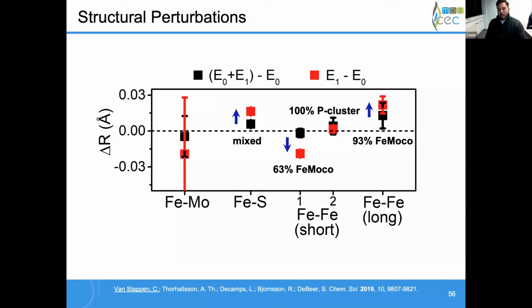and a little bit less so for the short iron-iron, but still reasonably. We also see that for the second short iron-iron distance, we really have no effective change, which at the P cluster makes sense, as we don't have any change in oxidation state.